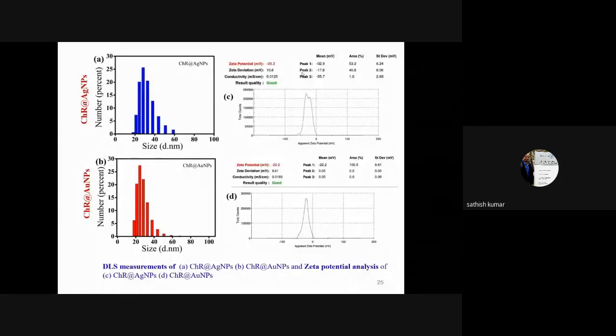So because of the large negative charge on the surface, the particles will repel each other. So it will prevent the aggregation of the particles. If two particles come close together, because of the negative surface charge on both nanoparticles, they will repel each other. So it is very important to synthesize particles with either a large negative zeta value or a positive zeta value. So here we found that the synthesized silver and gold nanoparticles were having large negative zeta value. And another study is the dynamic light scattering, which gives some information about the hydrodynamic diameter,